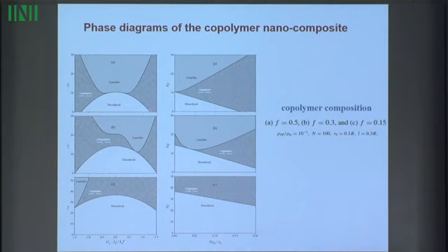And then in this way one can obtain the phase diagrams, where one can see what happens, for example, if one increases the concentration of nanoparticles, then basically the hexagonal phase is induced, or what happens if we increase and change the sign of the discrimination energy. So again, the asymmetric cases are when the block copolymer is asymmetric, when the length of one block is different from the length of another. Here the most interesting phase diagrams occur.